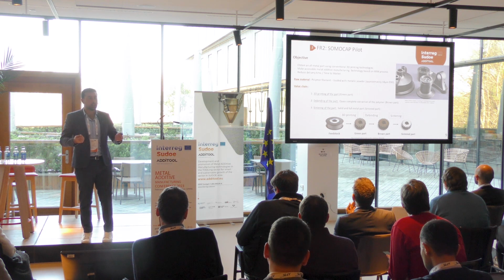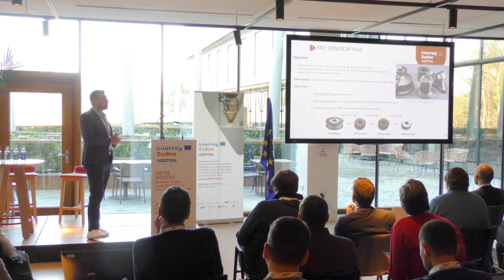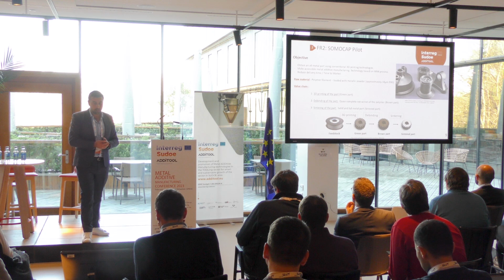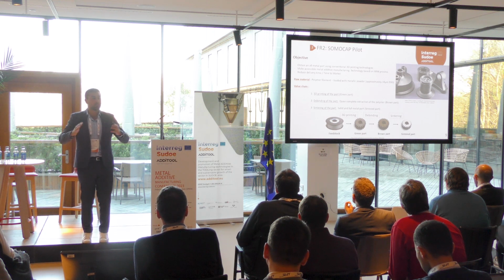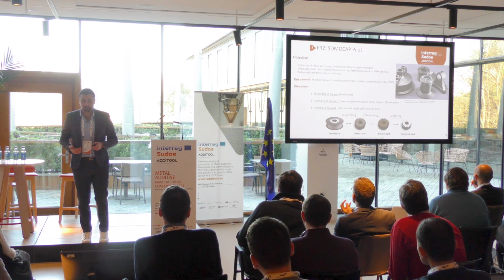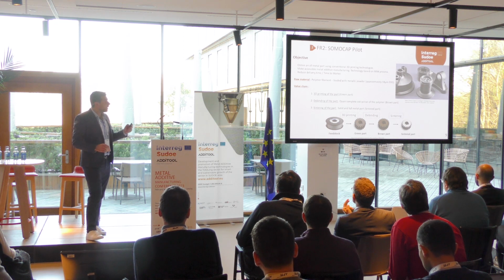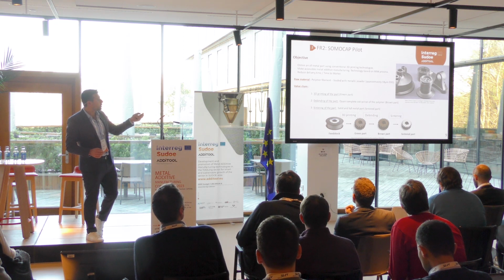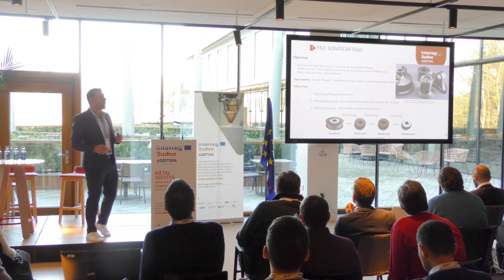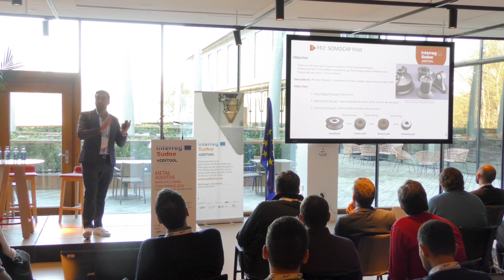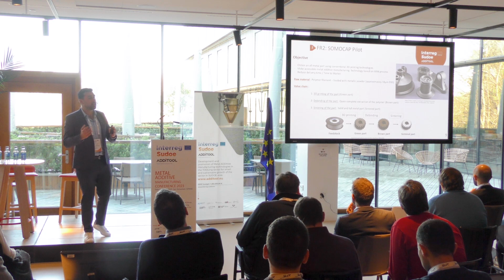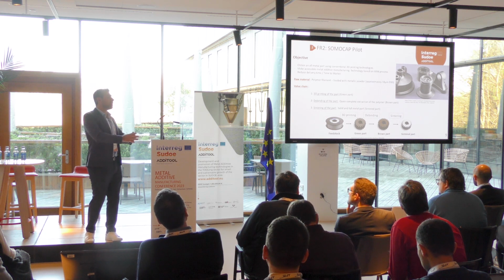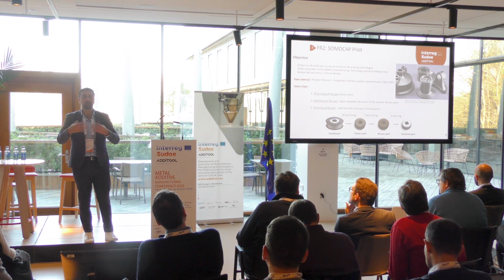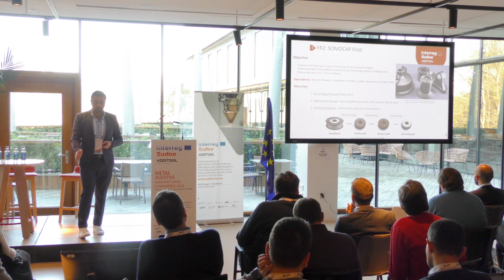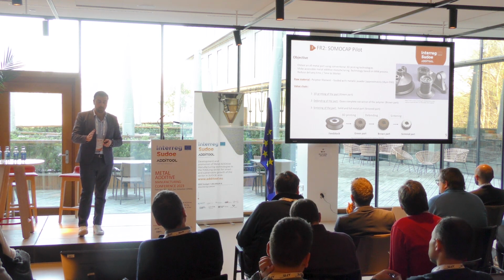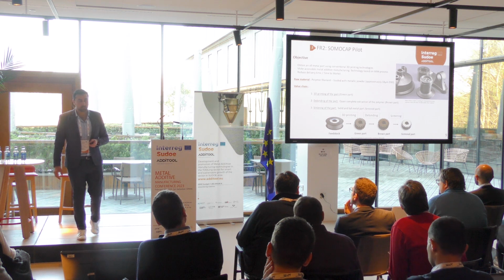Then we have to sinter just below the fusion temperature of the metal to obtain a solid and full part. This is the sintered part. Note that you have a reduction in scale. After the sintering process, and after the debinding also, you have to manufacture a bigger part so that at the end you have your tolerance. It's about between 19 and 26% approximately.